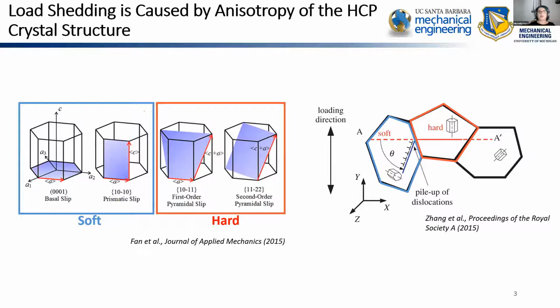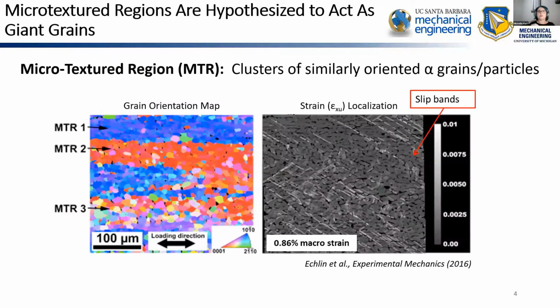And so this phenomenon is sensitive to both microstructure and temperature. And the particular microstructural feature that we're concerned with in this study is microtextured regions, which are defined as clusters of similarly oriented alpha grains. And so in this particular micrograph here from previous work at UCSB, you can see you have a soft MTR here and a hard MTR here, where all these grains are colored by orientation.